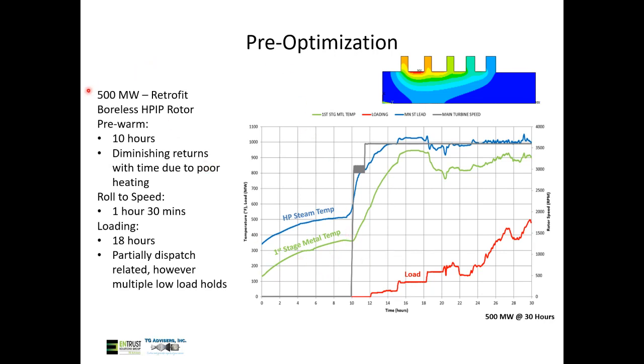The other thing that was interesting here is they had done a retrofit of the high pressure turbine, high temperature rotors, and they had not changed any of the startup practices. So as a result, they were being very conservative. A 10-hour pre-warm, then they go to speed very quickly, and then loading was about 18 hours, though some of that was dispatch driven, some of the low load holds. But you can see they were following the instructions of a low load hold, trying to get temperatures up that way.